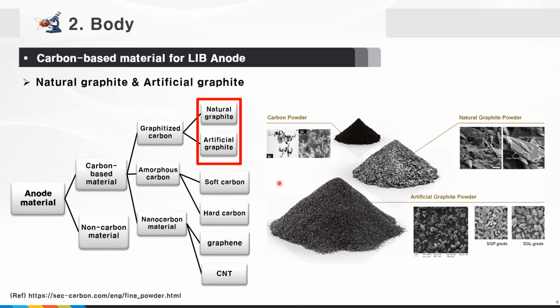However, by having a high capacity close to the theoretical capacity of about 365 mAh per gram, graphite, the amount of lithium entering and leaving per unit area increases and the rate characteristics are relatively degraded. Therefore, in products that require long-term life and high power characteristics, artificial graphite and amorphous graphite are mixed in a certain ratio, or anode active materials are used with only these products.